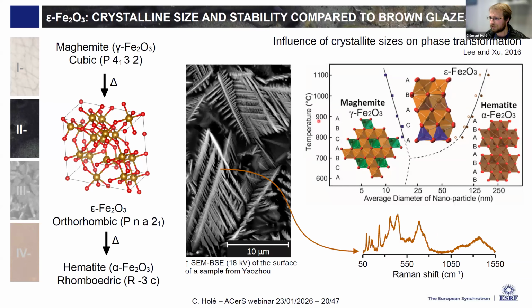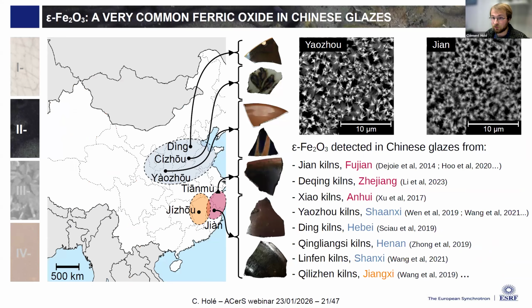In some of the ancient glazes, we have dendrites that are enormous compared to these nanosites. We are at more than 10 micron dendrites, but they still have this very characteristic Raman spectrum that was associated with iron epsilon oxide. So why so? And what's also very interesting is that this phase is actually super common in brown glazes.